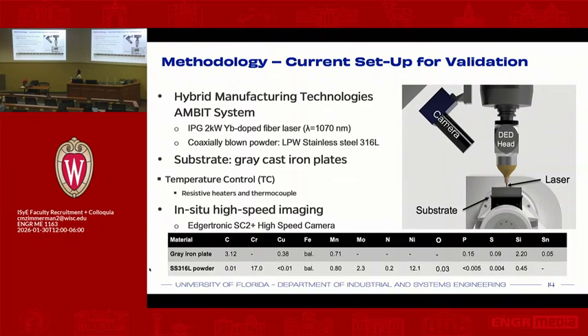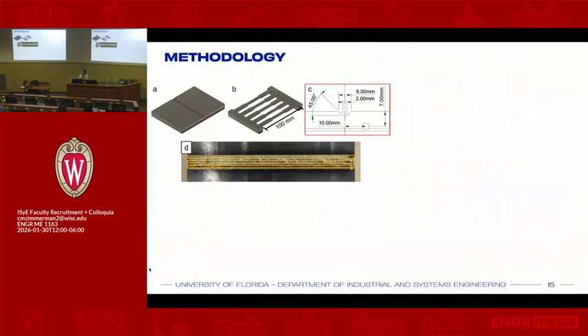And you can see that this is a smaller scale type of project that we did, and it was with gray cast iron. You'll see that we are able to take a look at a couple of things. So we did gray cast iron with stainless steel. We simulated a repair by basically creating a slot that you see here on A, and then we filled the slot. So in the middle of your tensile bar, you'll have the repair right there in the middle.